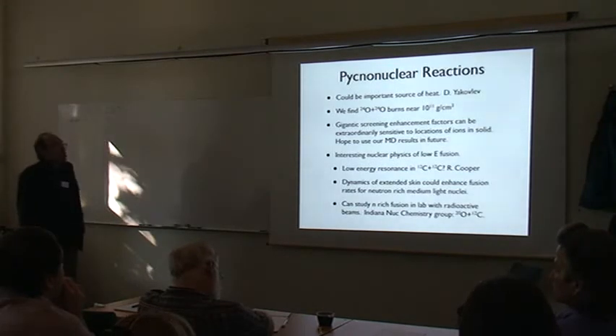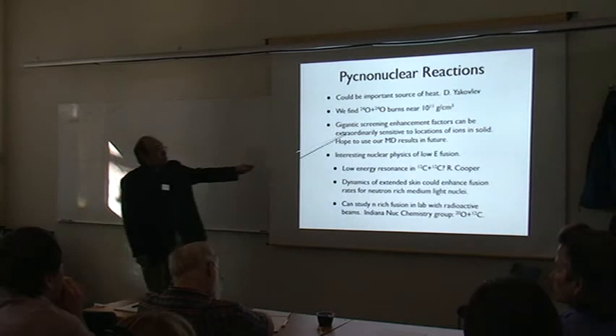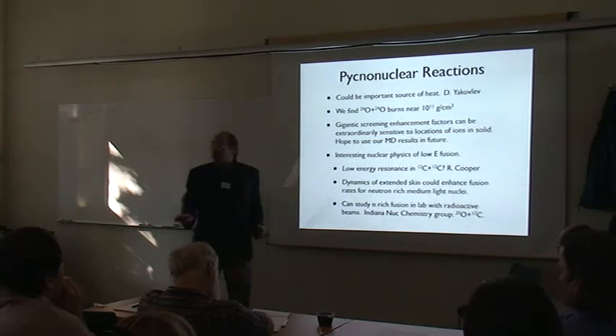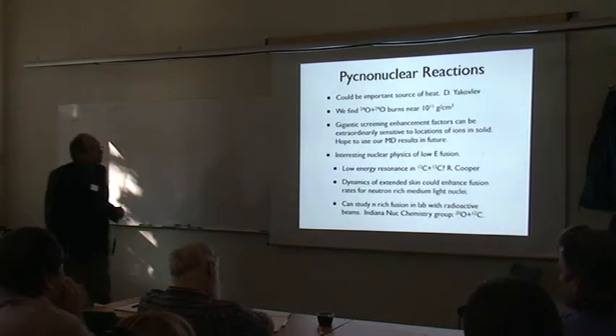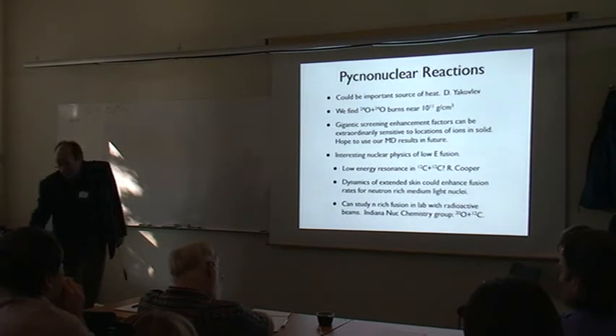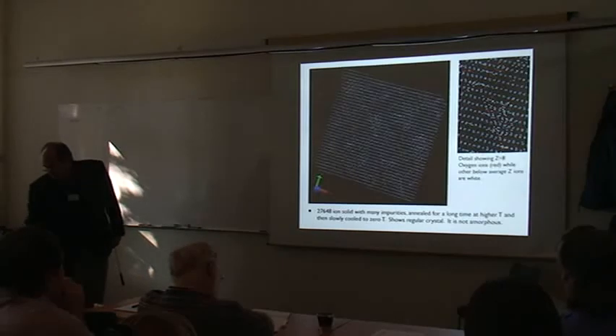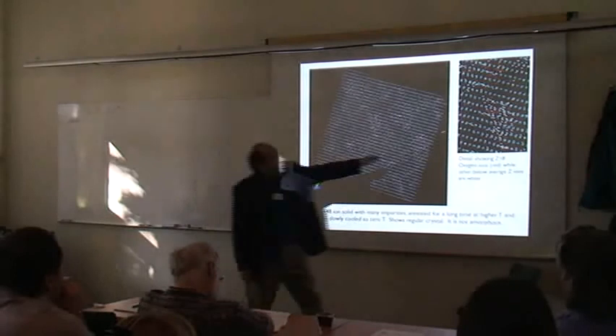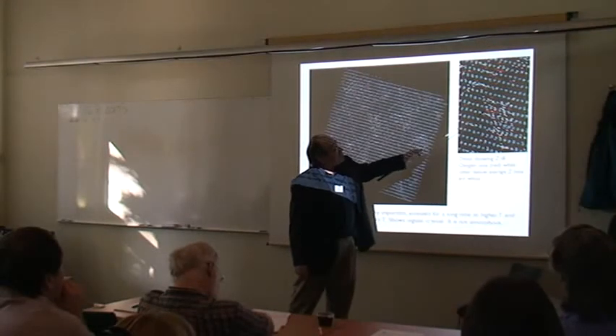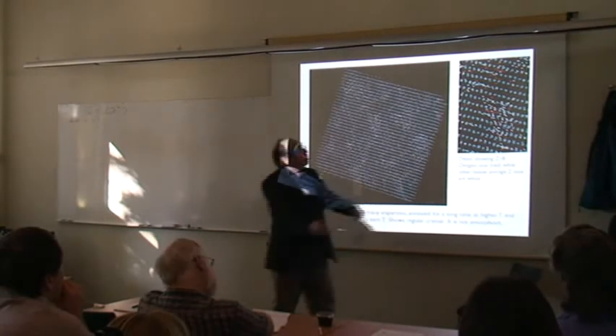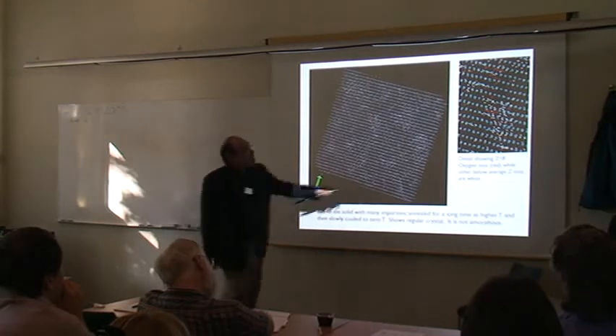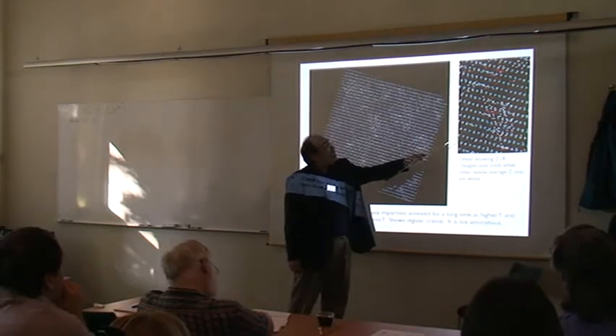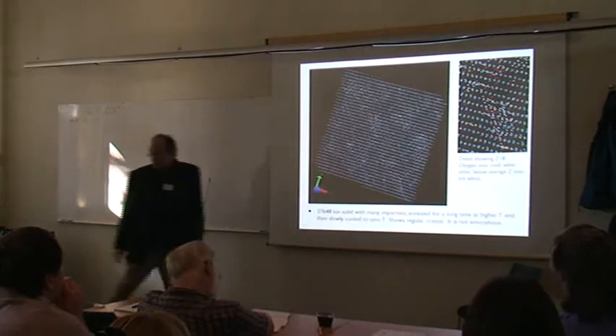And so these pycnonuclear rates can be extraordinarily sensitive to exactly where the ions are in the cell. Coming back all the way to here, you can see a bunch of oxygens that are kind of squeezed in between the other lattice sites, and so these oxygens can fuse at a relatively high rate.